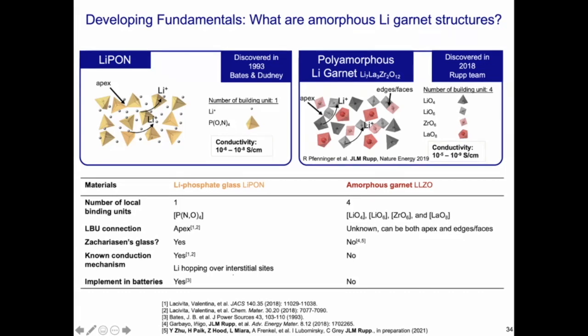But if that has been a long way, then the question is, well, lithium garnets do not have one building unit, they have even up to four. So they have the lithium on octahedral and tetrahedral sites, the zirconium on an octahedral site, and you have the lanthanum oxygen also in a dodecahedral site in the structure. So I was really fascinated. It's like going to a good zoo and watching an animal that becomes more complicated: how to describe the lithium diffusion in such an amorphous structure.